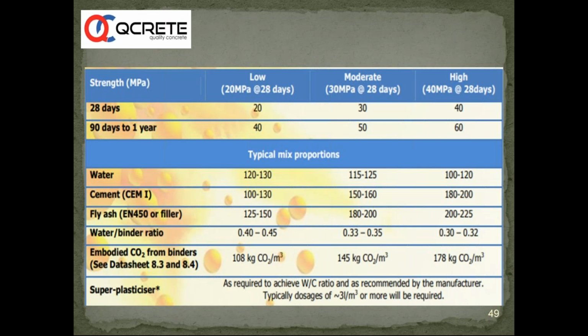So some of the high volume fly ash concretes, mix proportion guidelines have been given here, where you can have an M40 concrete with a very good amount of fly ash, lower amount of OPC mix actually. So all this is possible if the structural engineer or specifiers start looking from a different perspective. The strengths can be specified at 56 days or 90 days actually. And the benchmarking of 28 days should be kept in the background. Benchmarking should be done on 56 or 90 days.